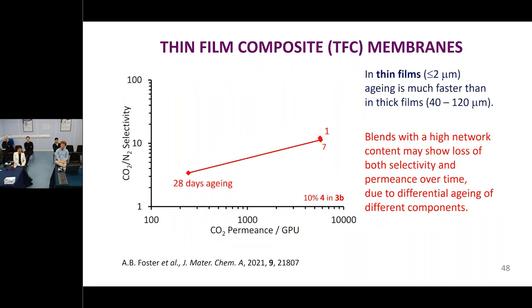But again, it all depends on how you do things. So here we've got a really bad example. This is exactly what you don't want in a thin film composite, where you've got a modest selectivity at the start and high permeance. Because this is a thin film composite, we're now looking in terms of permeance rather than permeability. And the odd unit for permeance is GPU, gas permeation unit, just as odd as that. But after just 28 days, we've not only lost a lot of our permeance, we've also lost selectivity. That's the last thing we want in the membrane. That's an absolute disaster.